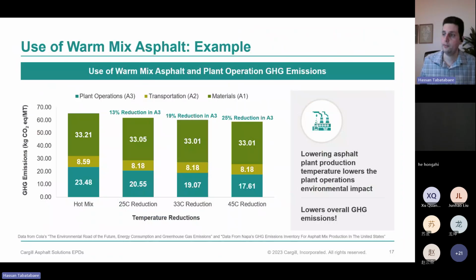As we're talking about carbon footprint, here's an example showing how different amounts of temperature reduction will reduce the carbon footprint of a warm mix asphalt. The reduction is in the A3 category, which is plant operation. That's where the fuel use is. And you can see that with a reduction of 25, 33, up to 45 degrees centigrade, we can get up to 25% reduction in the plant operation carbon footprint, which adds up significantly when you look over a total production of an asphalt plant over a year.